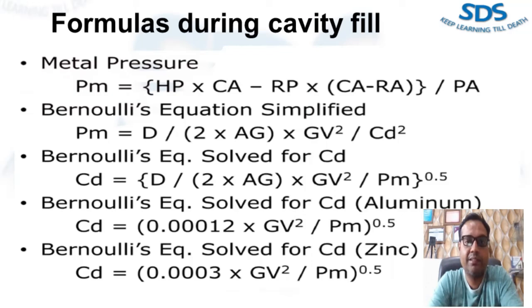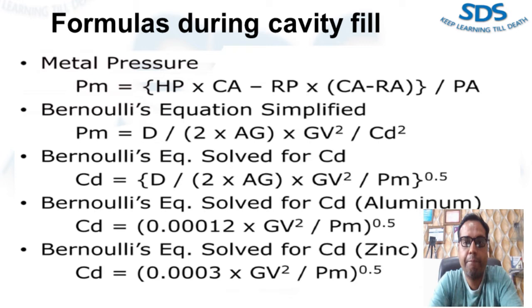To calculate Cd, the process monitoring system must accurately calculate the head side pressure average during cavity fill, the rod side pressure average during cavity fill, and the average in-gate velocity. Cd should be calculated every shot and tracked by SPC within the process monitor. A standard for the minimum Cd value should be established. As a rule of thumb, a good cold chamber standard minimum would be between 0.3 to 0.36, and a good hot chamber standard minimum would be between 0.45 to 0.5.